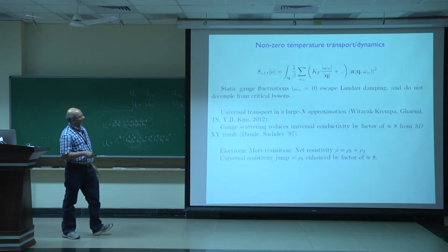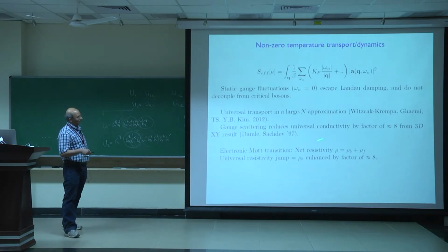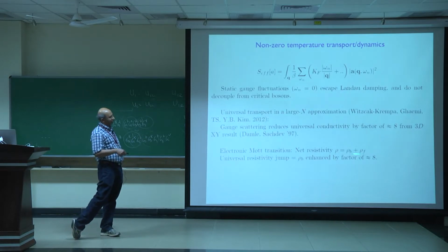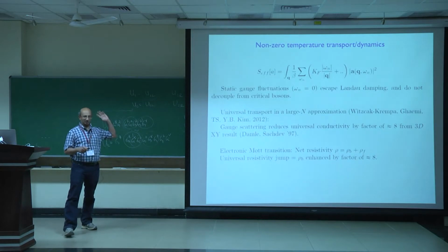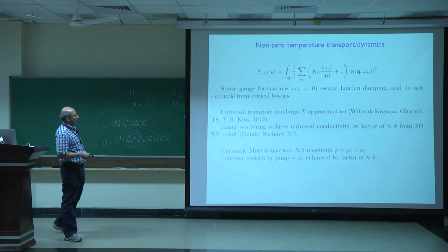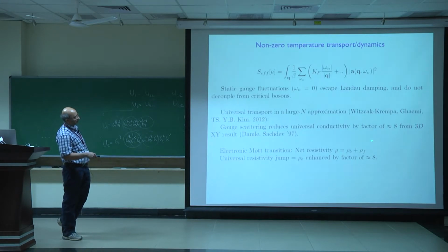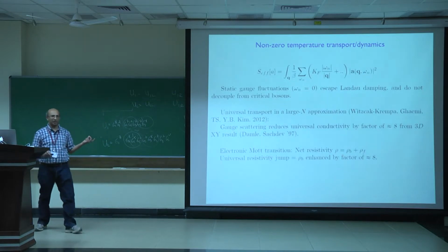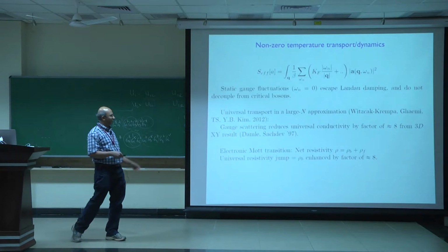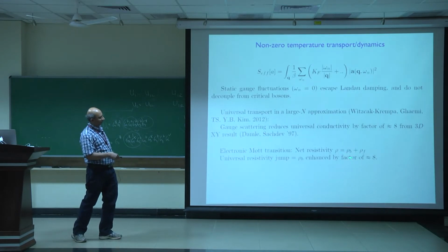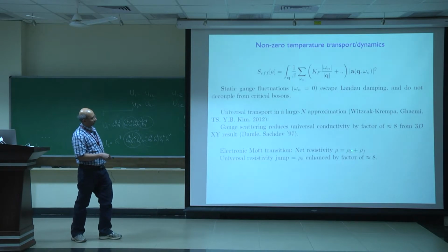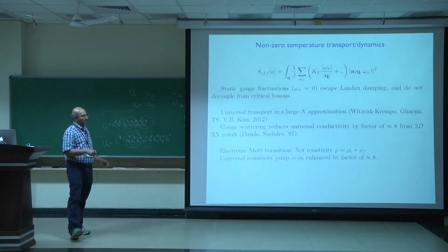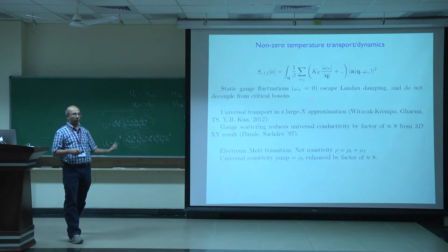So this actually enters experimental quantities. At the electronic Mott transition in this kind of slave particle theory, it's been known for a long time that the correct way to calculate the resistivity is to add together the resistivities of the boson and fermion. This is a rule going back to Ioffe and Larkin. So the reason there's a universal resistivity jump is that the fermion resistivity is not doing much across the phase transition, while the boson resistivity goes from 0 in the metallic phase, where the boson is superfluid, to infinity in the insulator, where the boson is an insulator. But right at the critical point, this is non-zero and is a universal constant. So consequently, as you approach the transition from the metallic side, this rho b jumps from 0 to a universal constant, and so experimentally it will show up as a jump of the residual resistivity by a universal constant.